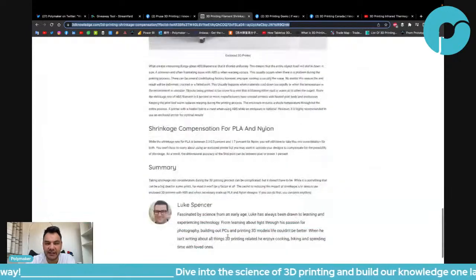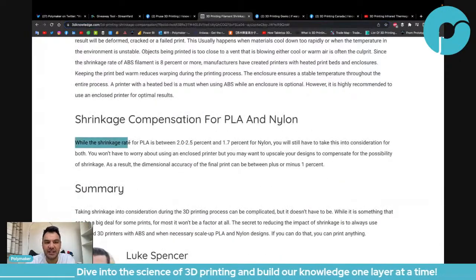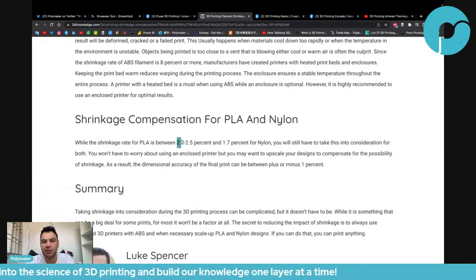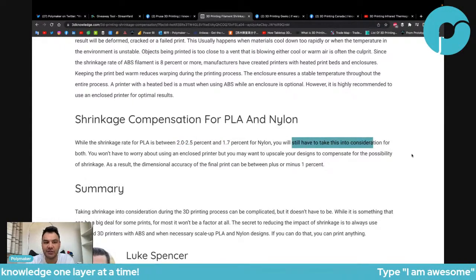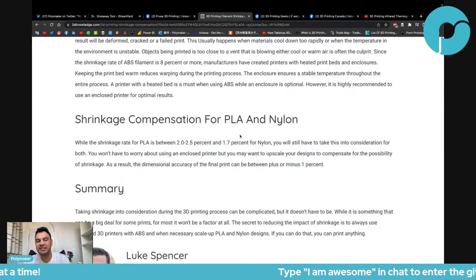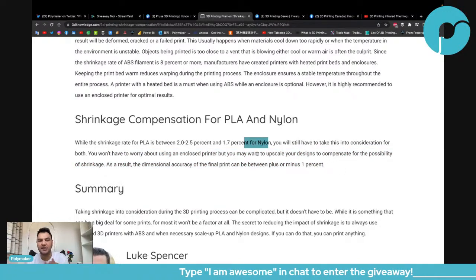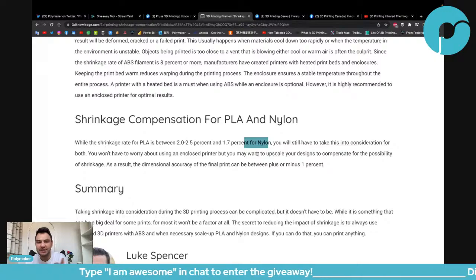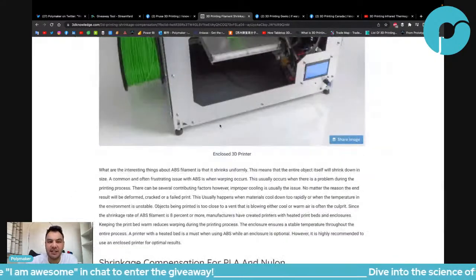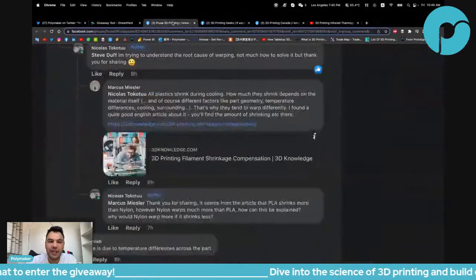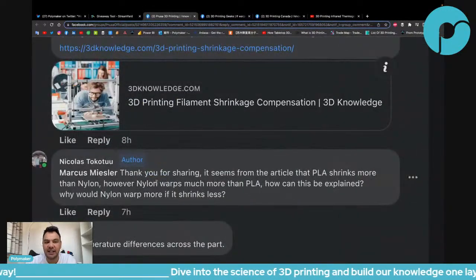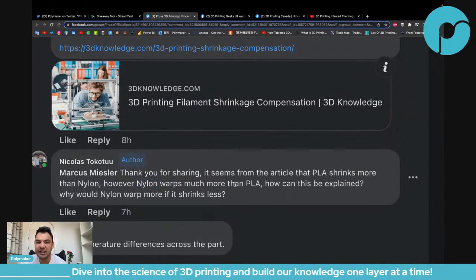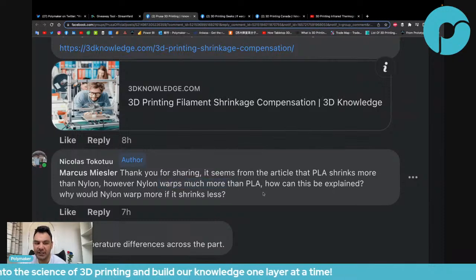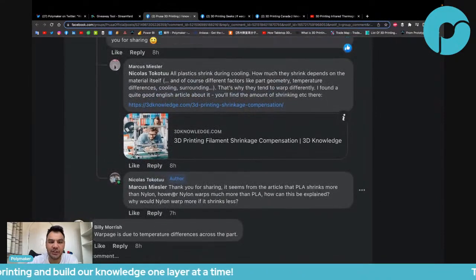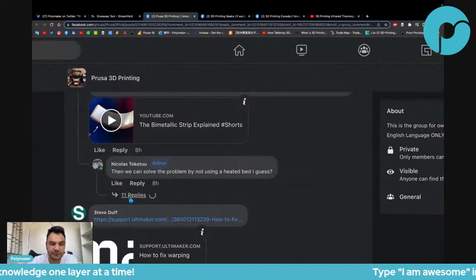However, inside they say while the shrinkage rate of PLA is between 2 to 2.5% and 1.7% for nylon, you will still have to take that into consideration for both. So they basically say for nylon you have to scale it up less than for PLA. So like I said, they don't really explain warping. But what I answered is, in the article they say that nylon shrinks less than PLA. Then why does nylon warp more than PLA? Unfortunately, I didn't have an answer, but that was my follow-up question.